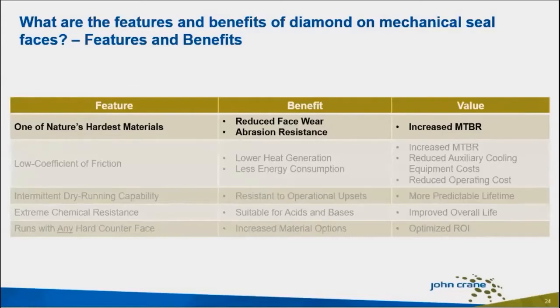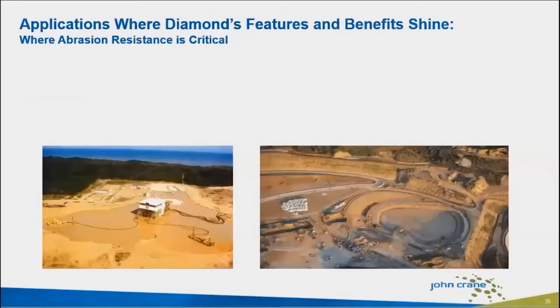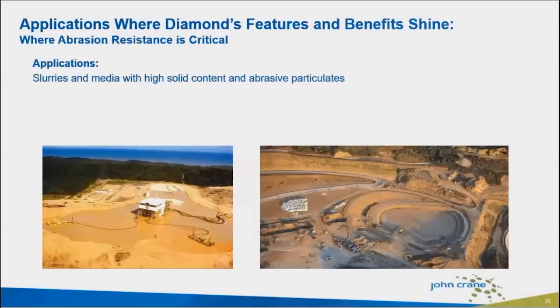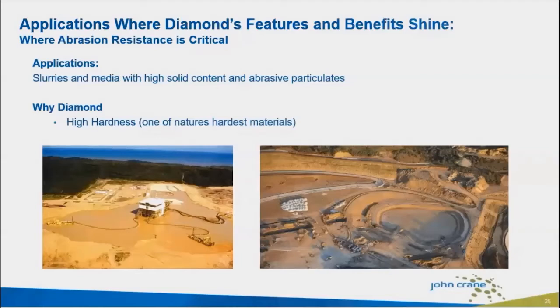Challenging applications where the hardness of diamond shines is applications where abrasion resistance is critical. So these applications include some of the most demanding abrasive applications in mining and mineral processes where the media contains solids or abrasive particulates. Our diamond face treatment is routinely being used in these applications and has even demonstrated that single seals with diamond faces in certain applications can effectively replace dual seals with processing media containing up to 70% solids. It also should be noted that diamond seals have given customers a cost-effective mechanical seal solution in applications where previously really only packing was used.